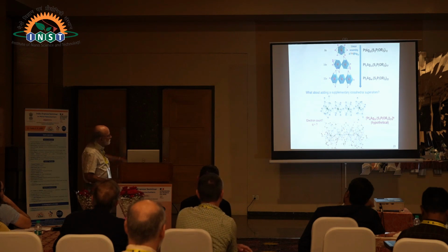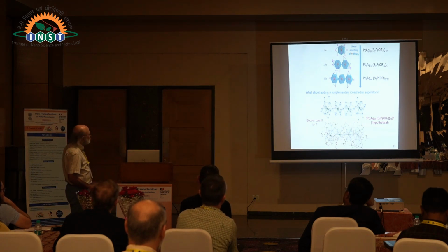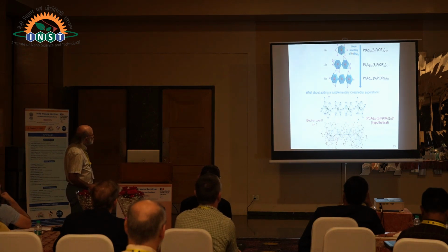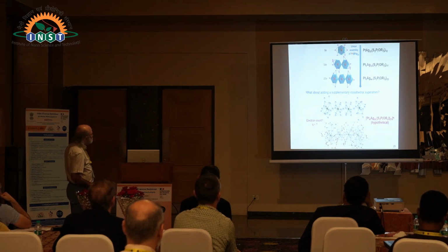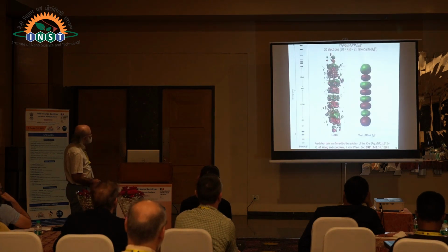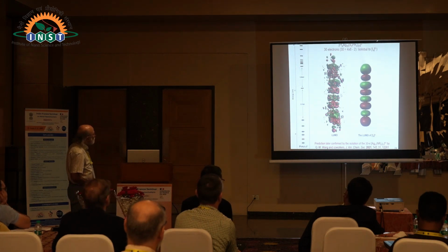We can do the same with 4 icosahedra. This is what we did. I'm going to just mention one case, starting from this molecule and adding another one, repeating the motif, and modelizing the outer shell similarly. We got this system, and we looked for the best electron count, for the best charge, actually. And we found it is -2. -2 corresponds to 30 electrons, and it's isolobal, isoelectronic, equivalent to the I4 ion, which is linear.